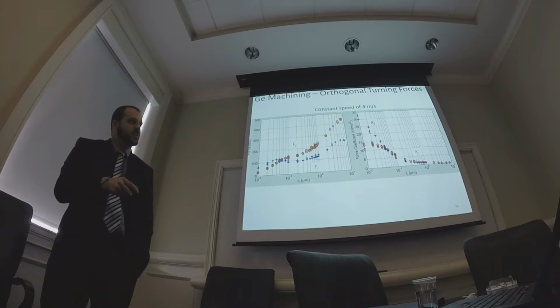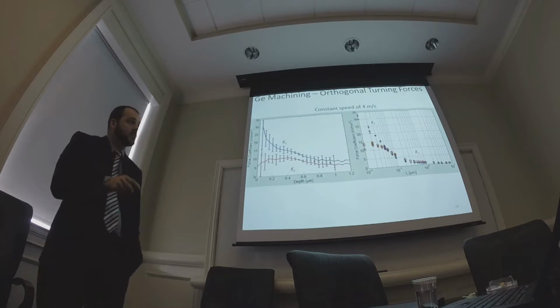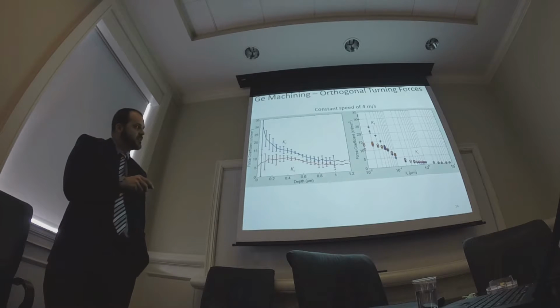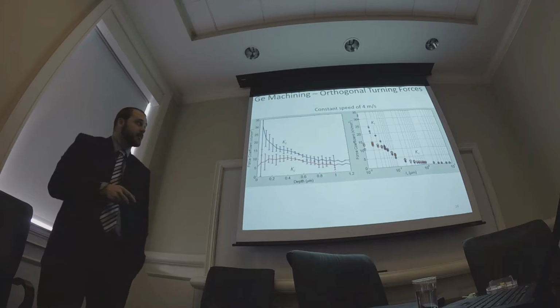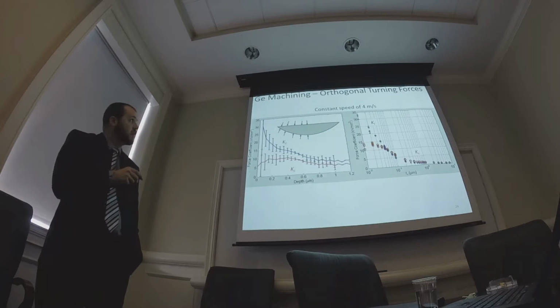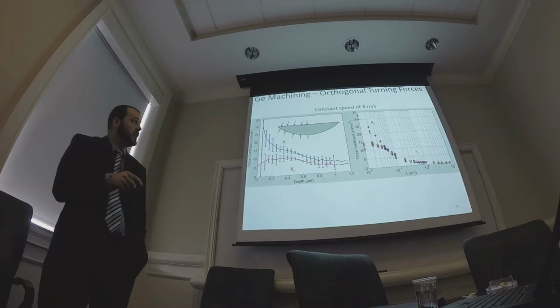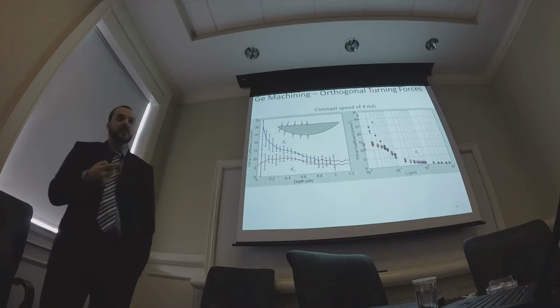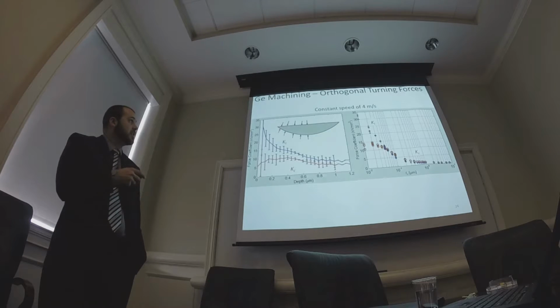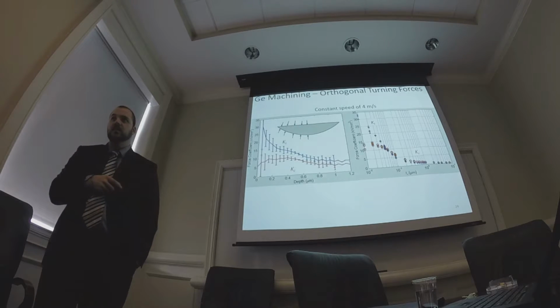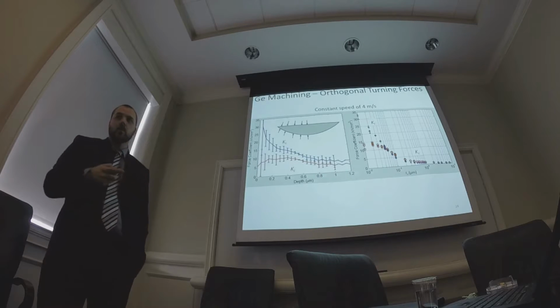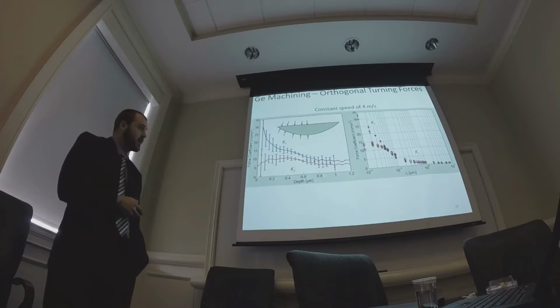In the orthogonal cut, we're seeing significant amounts below that. Now we did go higher in chip thickness here, and this does seem to still keep going down, but the drop is much less severe. The reason is with the round nose tool, we have every chip thickness from 0 to our maximum chip. So we're taking force coefficients from this orthogonal diagram, and force per area is greater here than it is here. It seems to make sense that as you continue getting deeper, you still have a 0 chip thickness, so we're still working in this range no matter what you do with a round nose tool. The orthogonal cutting seems to give us more information about the actual cutting mechanics.